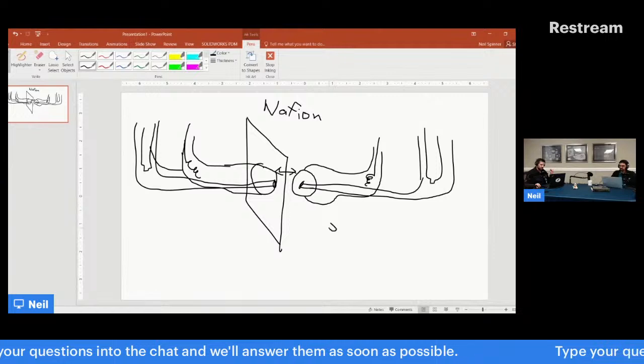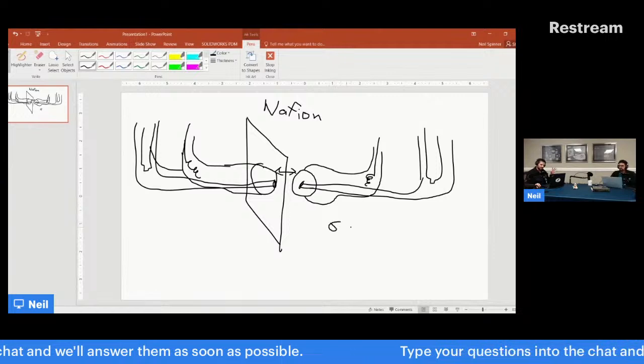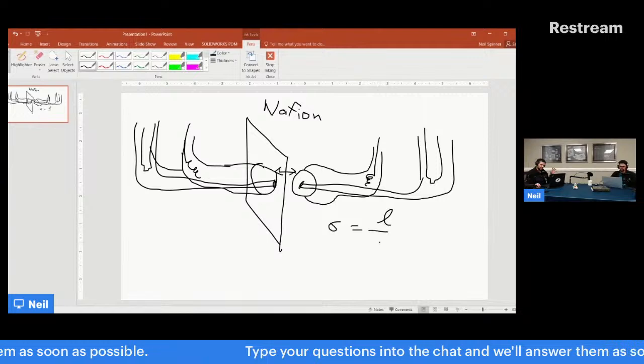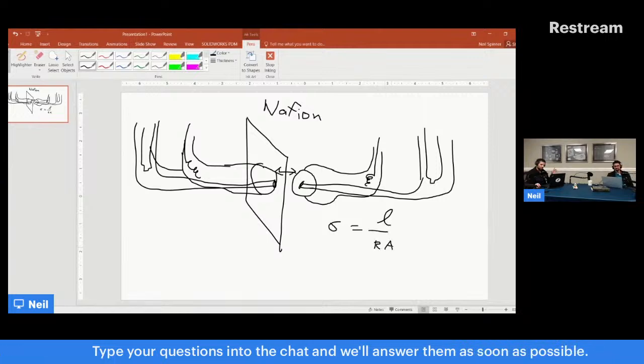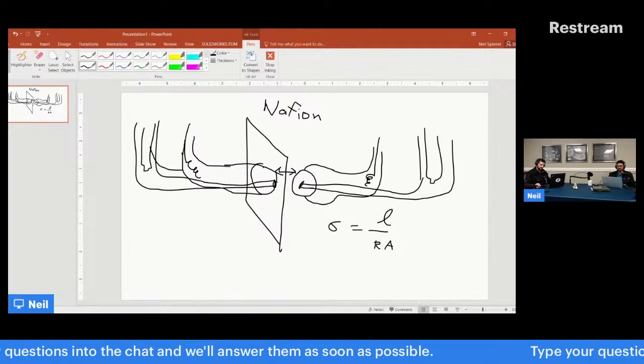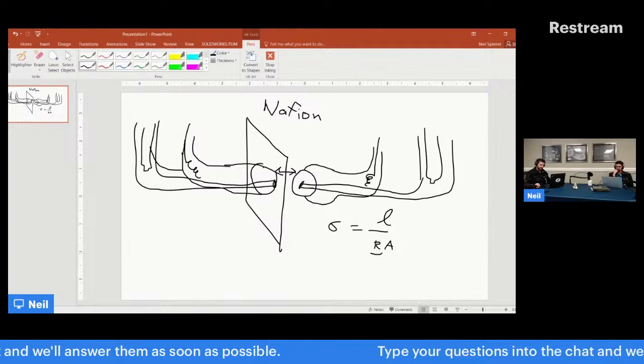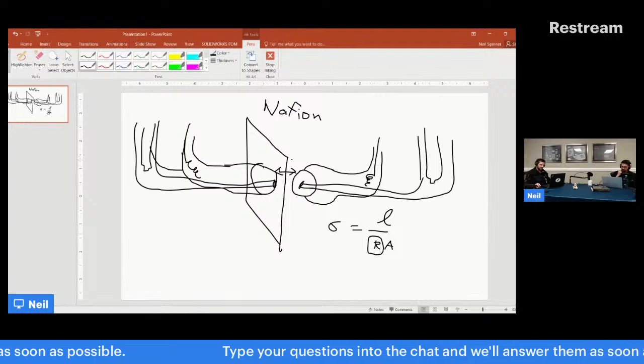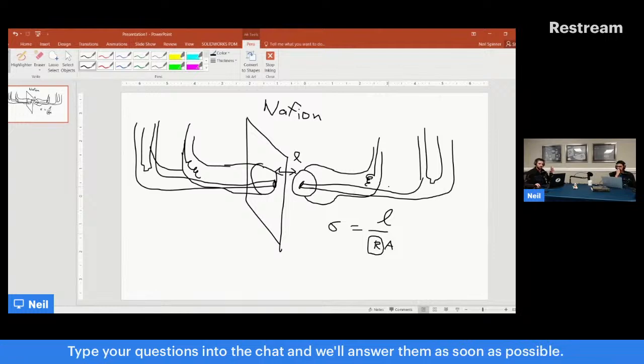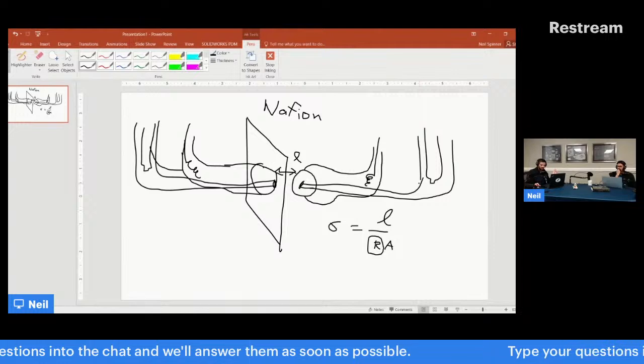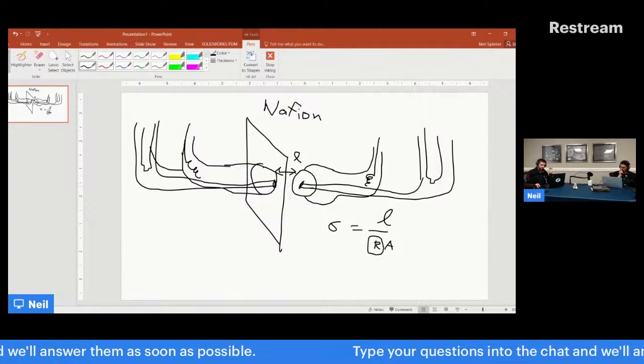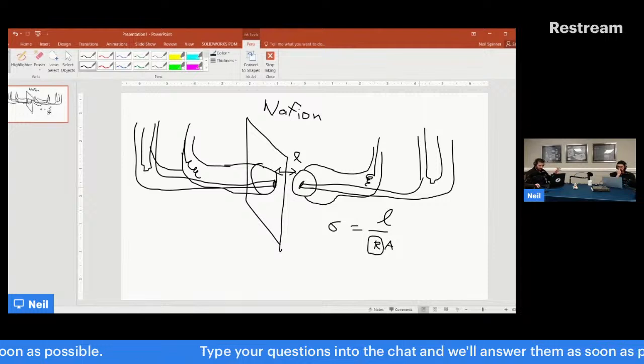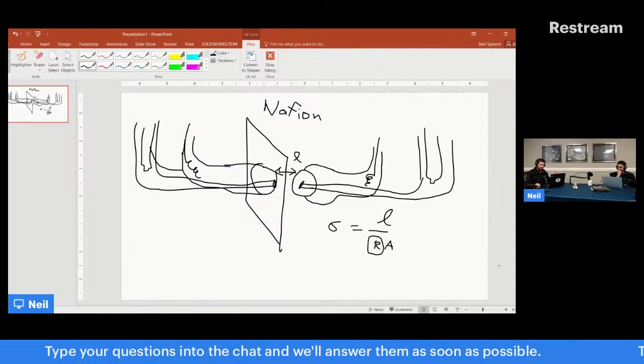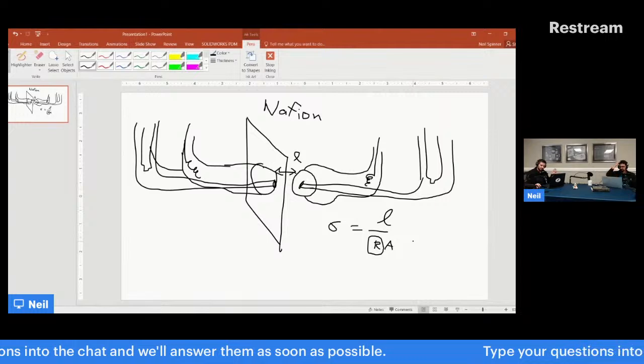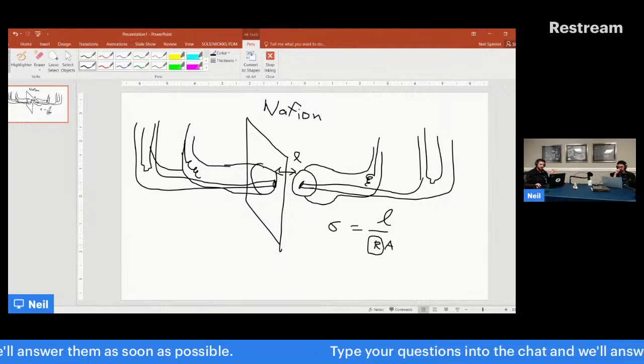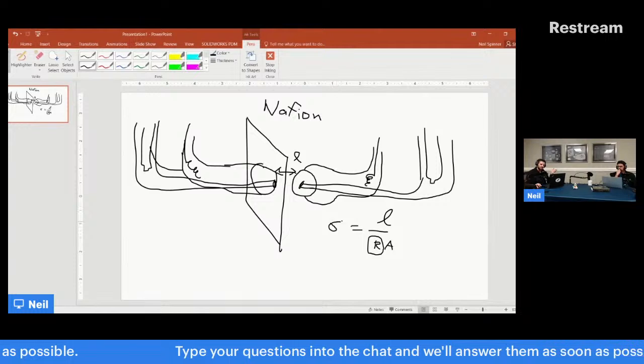And you get a measurement of the conductivity, which is L over RA. A is the exposed surface area, R is the resistance, and L is the distance between the two. So you're getting a measurement across a very short distance, facilitated by these long Luggin capillaries across the membrane, and you do an impedance measurement or a very short cyclic voltammetry. You get a measure of the resistance. You have the exposed surface area, and you can get a measure of the conductivity. So that's what you're after.